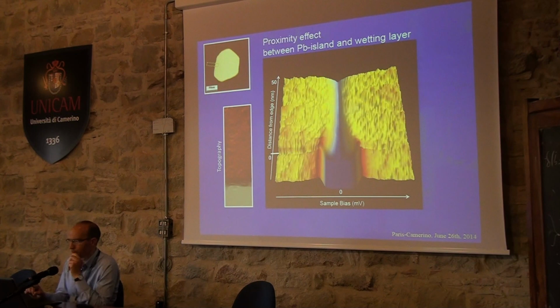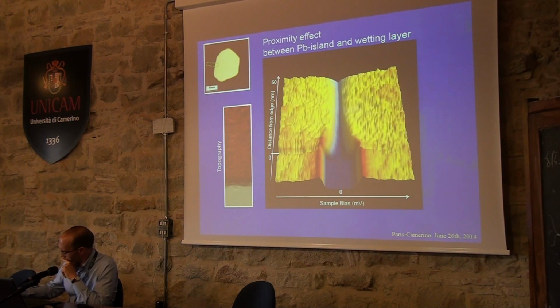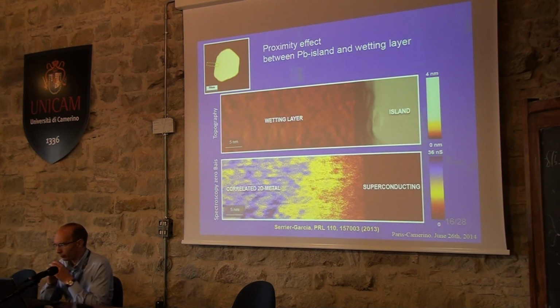So we study the proximity effect between these superconducting islands and this disordered correlated metal, and you see on this three-dimensional plot that when the tip is situated on the superconducting island, you see a very nice superconducting gap with coherence peaks, which are plotted in red here. But immediately, when you leave the island and you appear on the proximity layer, the superconducting gap becomes a proximity gap, and then smoothly evolves into the Altshuler-Aronov anomaly.